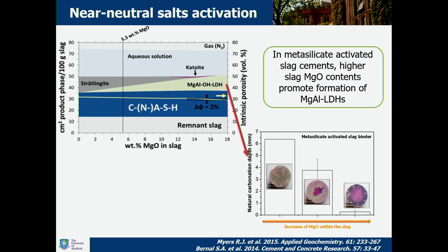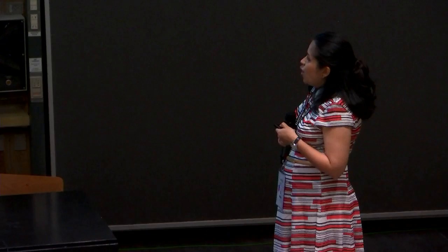To understand the mechanism driving this type of behavior, we went back to analyze what's going on in the alkali activated slags when we use metasilicate. So via thermodynamic modeling, we can predict that as the magnesium content within the slag increases, we favor formation of these phases, magnesium aluminum layered double hydroxides or hydrotalcites. And we identified that in the slags with higher contents of magnesium, the natural or accelerated carbonation of these materials is significantly reduced. So we know that there is an interaction between the hydrotalcite and the CO2 present in the system. So if we consider that when we use sodium carbonate activator, the activator is actually providing carbonates to the system, it's more likely that those carbonates are chemically bound by these phases.